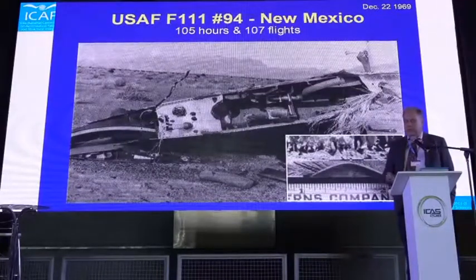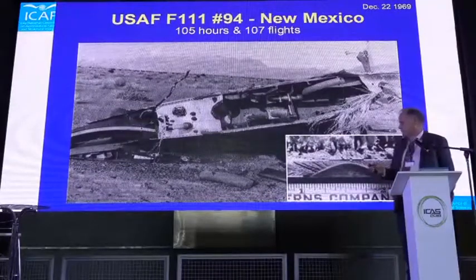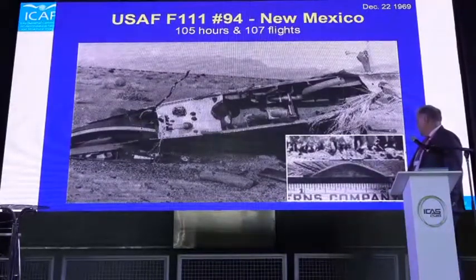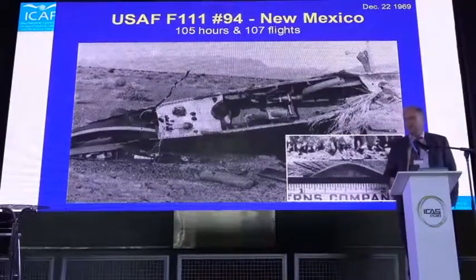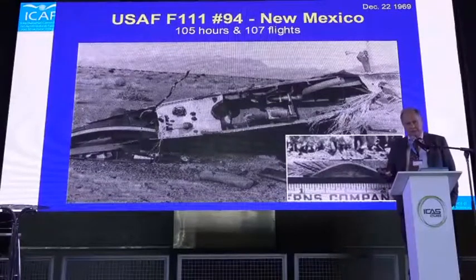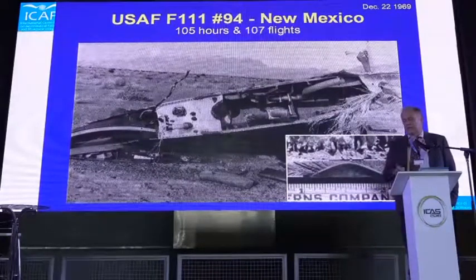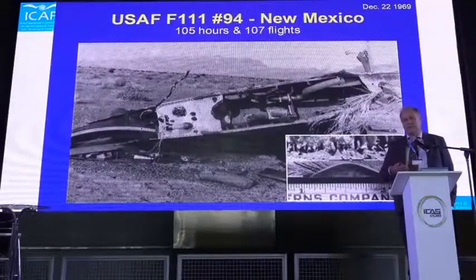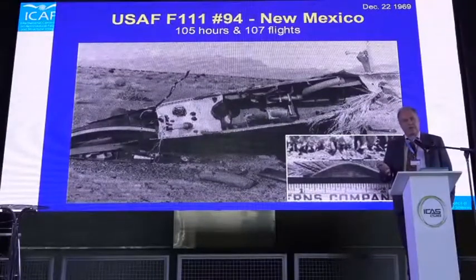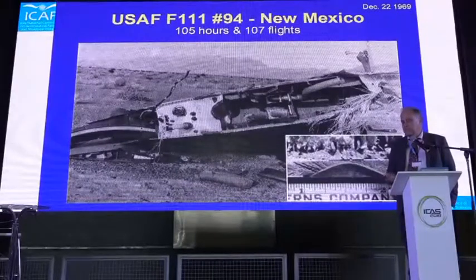And the reason, of course, you can see down on the lower corner here, sorry, I can't get this right. You see, on the right-hand side, you have an initial flaw present in this steel. It's a D6 steel, already at the beginning, roughly 1 inch long. And this particular steel is very sensitive to small cracking. So failure occurred very fast. Eventually, the problem was sorted out, and they have done 4 fatigue lives and resumed safe flying. But each and every aircraft had to be tested at minus 40 Fahrenheit before flying, due to the sensitivity to very small flaws. Very expensive.